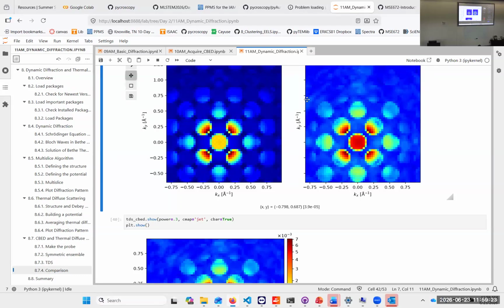If you want to simulate that, you just let the atoms not wiggle as much. So you reduce the Debye-Waller factor, the deviation from the ideal position, and then you can see how much that influences it. And if you heat it up, you see it even better.